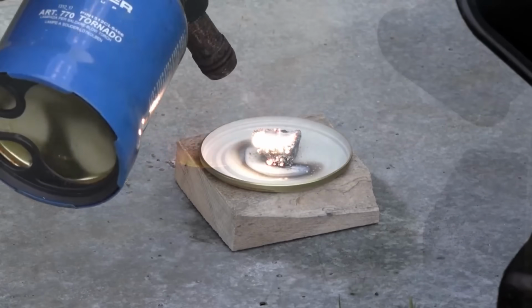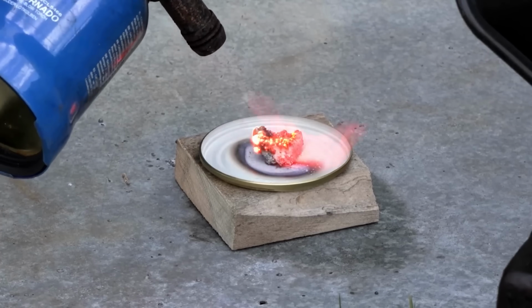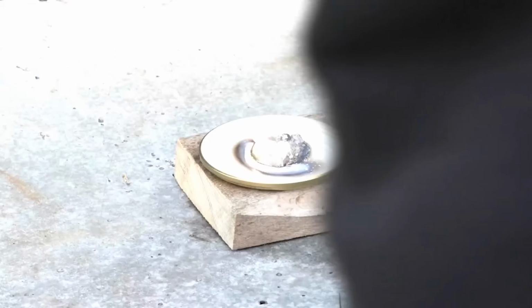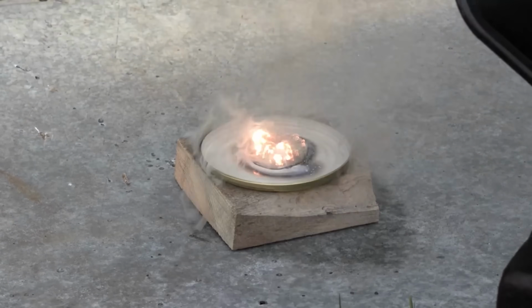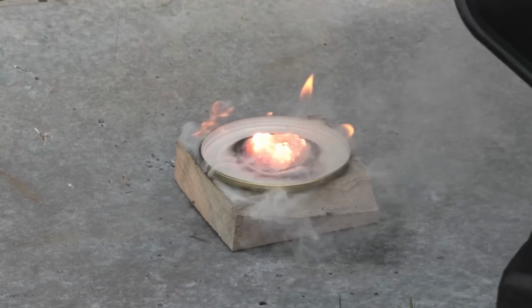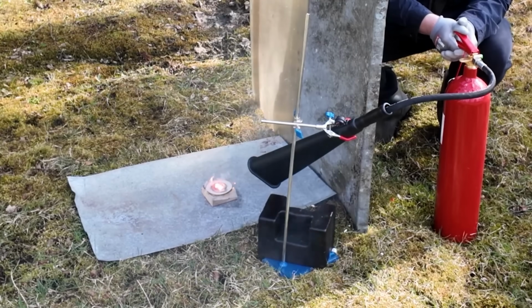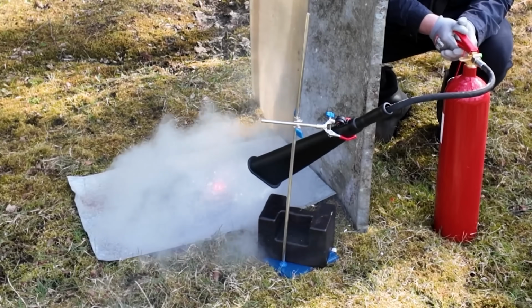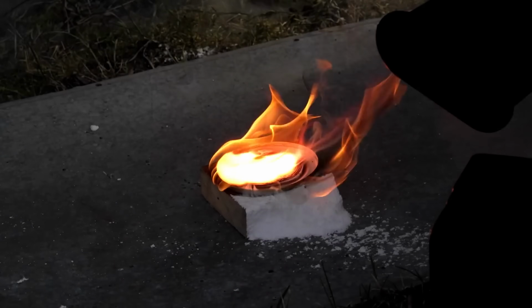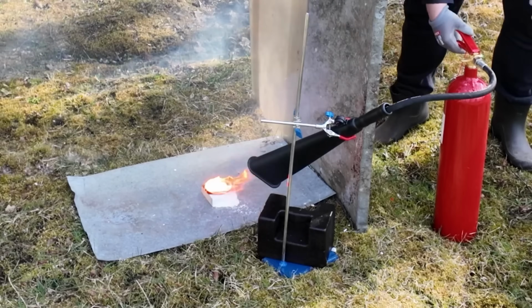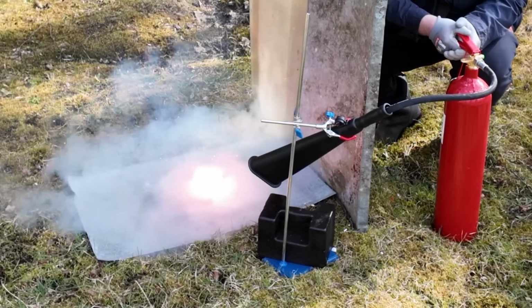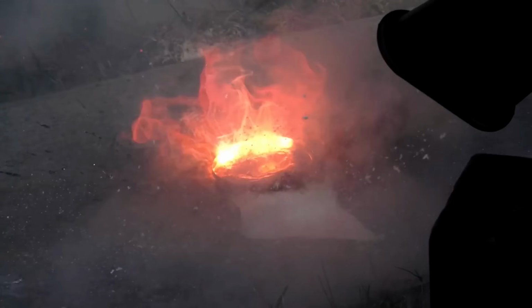Can less active lithium be extinguished with carbon dioxide? After ignition, lithium slightly melts, after which it starts burning with a bright white flame, which is intensified by carbon dioxide. You can see a pile of dry ice on a tin in the plate at the bottom, but even a strong flow of carbon dioxide can't extinguish burning lithium.